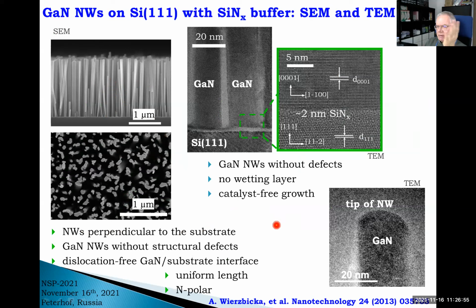Gallium nitride nanowires, which are usually, let's say, up to 3-4 micrometers long, pretty dense. Density is difficult to control. And on the top images, you see that there is this silicon nitride film in between silicon and gallium nitride. You see it always, also here. This is something like a 2 nanometer thick silicon nitride film. This nitridation is self-limited, so usually it goes to 2 nanometers and then the process stops. There are no dislocations at this interface with silicon nitride. I will come back to this point later on.